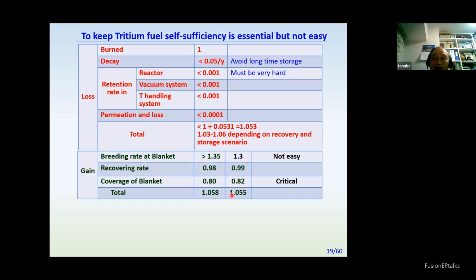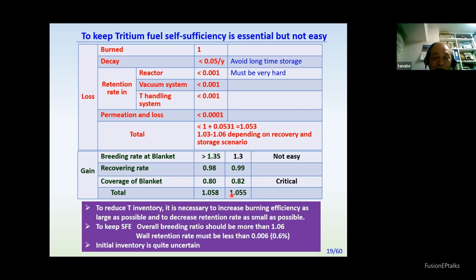So at steady state, to reduce T, it seems self-sufficiency would be satisfied, but for tritium inventory, to reduce tritium inventory it is necessary to increase burning efficiency as large as possible and decrease the retention rate as small as possible. To keep self-sufficiency, the breeding ratio should be more than 1.06, and the retention rate might be less than about 0.6% or so. Initial inventory is also important - this is steady state inventory, but initial inventory, as I'll show later, also becomes important.